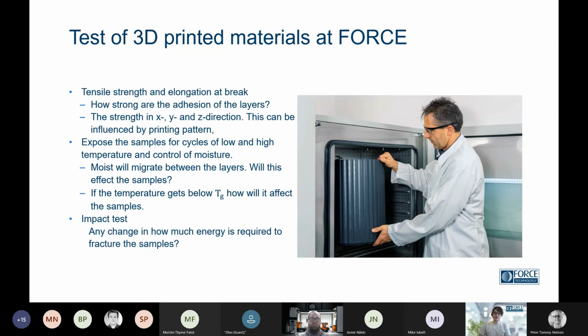We can also use this to check what would happen with the product if we get below Tg for some of the materials used for 3D printing, and how it will affect the samples. And we can also use some impact tests after we have done this climate testing to figure out how much energy is required to see a fracture in the sample, and then we can compare if it's still very resistant after it's been exposed to these different cycles in the climate chamber, or if it's been significantly worsened.